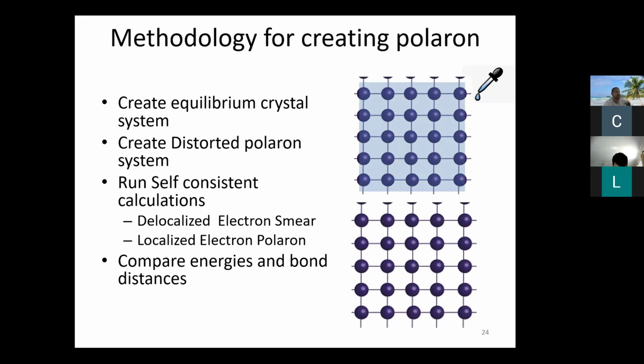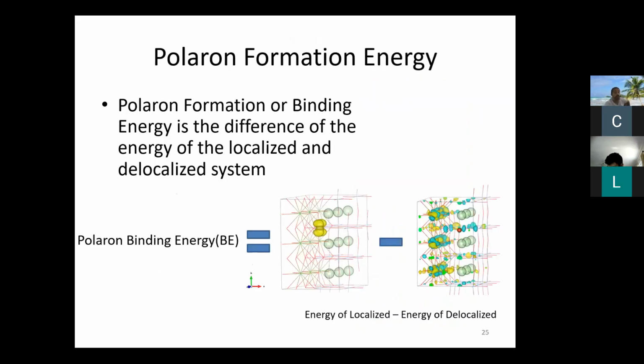So what I have to do manually is distort this system, kind of how a polaron would look. Remember, if I push the oxygens away from a titanium, that's going to create a more positive field in the middle. Once I smear this electron over, after a while of running this self-consistent calculation, it will localize in the middle. Comparing these two energies gives us a polaron formation energy, which is highlighted here.